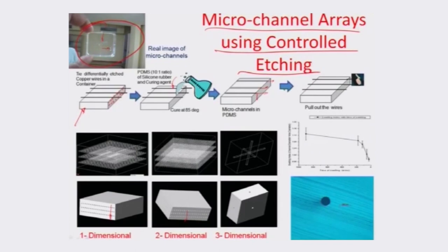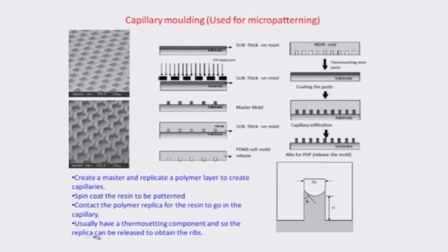The only issue is swelling the PDMS matrix and shrinking it back. The circularity of such a channel is well retained. A solvent is used to expand the PDMS, and when the solvent evaporates the PDMS deswells back while maintaining the aspect ratio of the structures and features. This is a very important technique for realizing arrays of micro channels in the bulk volume of the PDMS matrix — an extension of replication and molding into the third dimension.